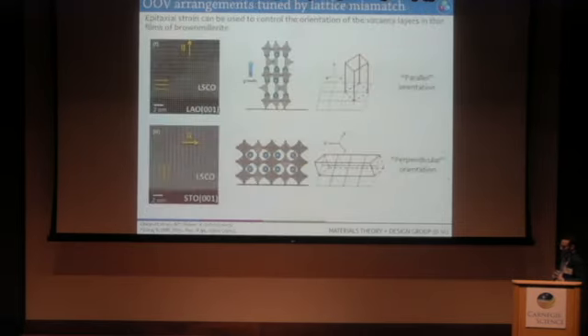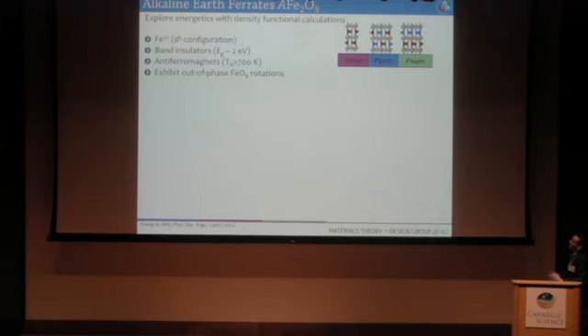The added nuance that I just want to mention is that these oxygen vacancies can order in thin film form depending on the strain state. So you can have the oxygen vacancy structure ordered in this direction, or it can sit in the plane. And this has been seen experimentally, and one can also probe this computationally. So let me get to some of the results now. What we've been looking at then are these ferrite compounds for calcium and strontium.